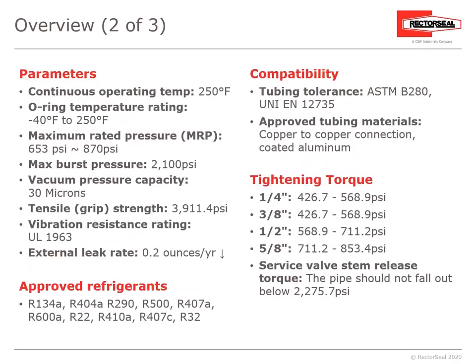It has a continuous operating temperature up to 250 degrees Fahrenheit. The O-ring temperature rating -40 degrees to 250 degrees Fahrenheit. Maximum rated pressure up to 870 psi. Maximum burst pressure 2100 psi. Vacuum pressure capacity down to 30 microns. Tensile grip strength 3911.4 psi, and then it's had the vibration resistance rating according to the UL 1963. It has an external leak rate 0.2 ounces or less per year. The approved refrigerants R134A, R404A, R290, R500, R407A, R600A, R22, R410A, R407C, and R32.